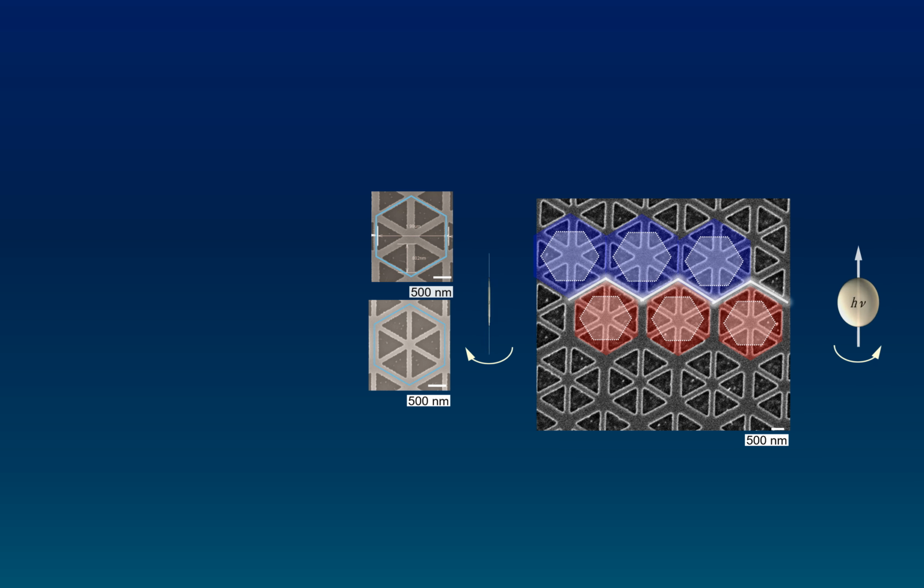Specifically, the photonic crystals were designed by the finite element method and fabricated in a 0.4 micron thick silicon thin film using electron beam lithography. Their properties were verified by high-resolution infrared reflection measurements.